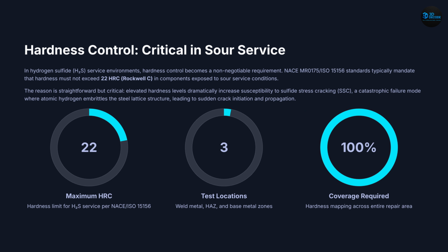Slide 5. Hardness control. Most important. This is a golden rule in oil and gas. Maximum hardness equals 22 HRC in sour service. Why? Because higher hardness, higher risk of SSC. And SSC is not gradual failure. It is sudden, catastrophic failure. That's why hardness testing must be done in weld metal.